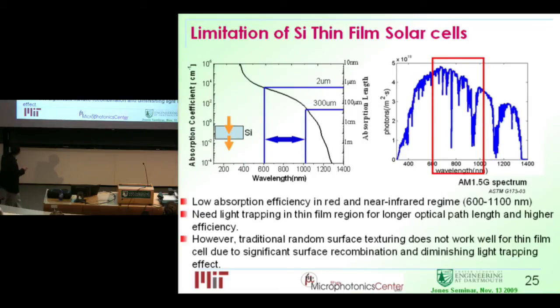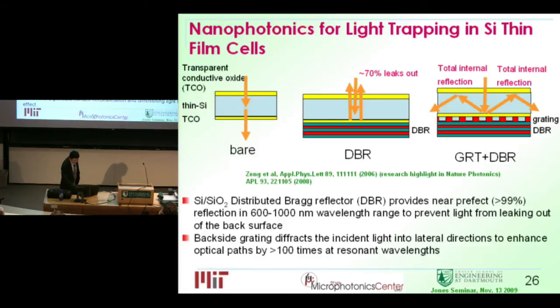One way is to get random surface texturing so that you can scatter light in lateral direction. Turns out this technique works really well for bulk silicon cells, but for thin film it doesn't work anymore, because if you get too much roughness, you increase the surface area of the semiconductor material. And I think it's Pauli who said, God created a crystal, it's the devil who created the interface. So at the interface, you have many dangling bonds, many defects that will eat up the photocarriers generated. So this technique does not work well anymore. You can get a few percent increase in efficiency compared to a flat cell, but it's much less efficient.